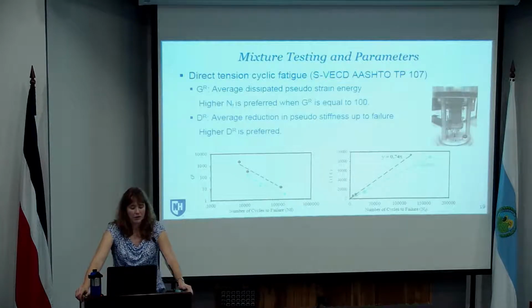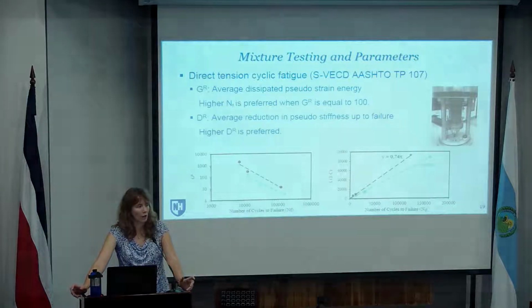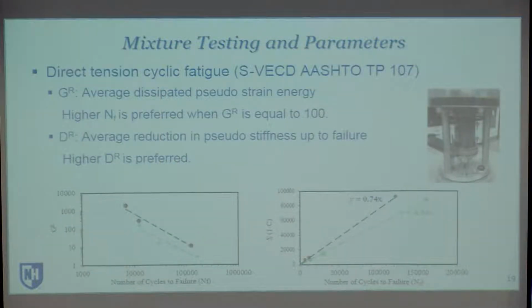In terms of the mixture testing parameters, okay, for complex modulus, again, similar to complex modulus for binders, we're looking at stiffness and phase angle. And then for the direct tension cyclic fatigue, for the SVECD approach, okay, there's a couple different parameters that we're looking at. One is the average dissipated pseudostrain energy and looking at how that's changing with the number of cycles to failure. And then more recently, we've moved to the newer protocol or newer parameter that they've identified, which is the average reduction in pseudostiffness up to failure.